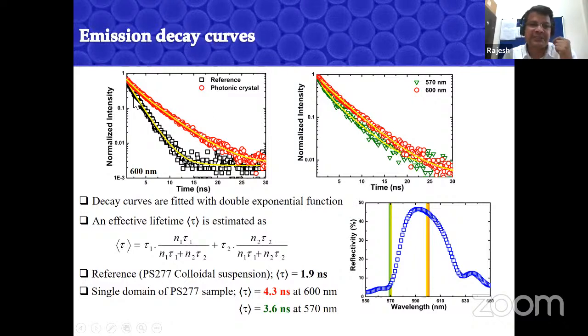And so I measured the decay rate first from the reference, which is a suspension. It gives you a nice decay. Basically, you excite, the emitter goes to the excited state, and you have a watch. You are looking at how much time the emitter takes to come down to the ground state. So it's around 25-30 nanoseconds. The emitter has completely come down. If you give it energy again, it will go again to the excited state. So the black curve is the curve you get from a reference sample. And you fit, and you get a lifetime of 1.9 nanoseconds, which is a typical lifetime of a dye, measured by anybody who works in this field.